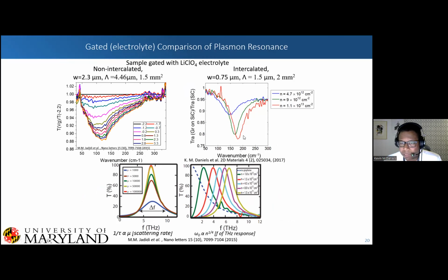So these are around 40 or 50, again, a consequence of the patterning. And we're able to gate it from 10 to the 13 going down to about 5 times 10 to the 12. And we're able to cover a good bit of ground through just very, very simple means. This is using electrolytic gating in this case. And so, we're able to demonstrate not only that, yes, we can improve this resonance through improving the carrier mobility, but also through gating, we're able to shift this plasmon resonance, pretty much to the letter of what our equations are telling us.